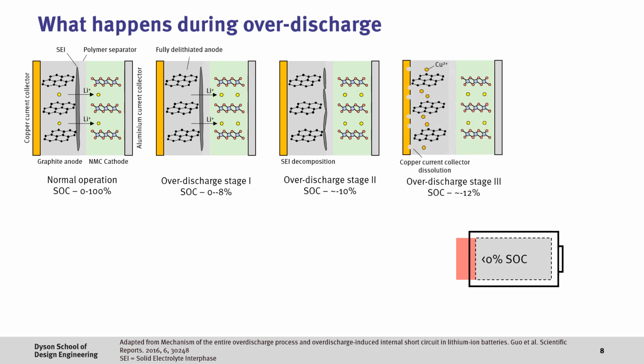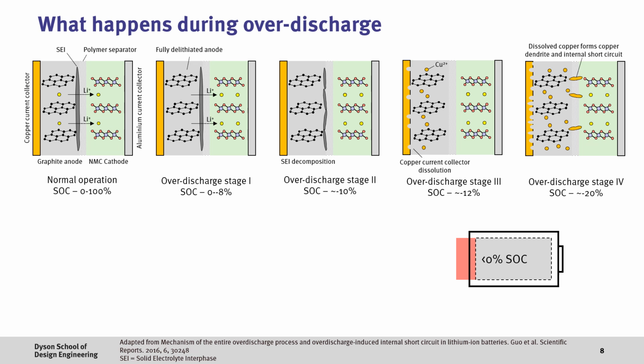As we continue, we run out of lithium, and then the copper, which acts as the current collector, starts to dissolve into the electrolyte. As we continue this, it can eventually form copper dendrites, which can internally short-circuit the battery in a similar way to lithium dendrites.